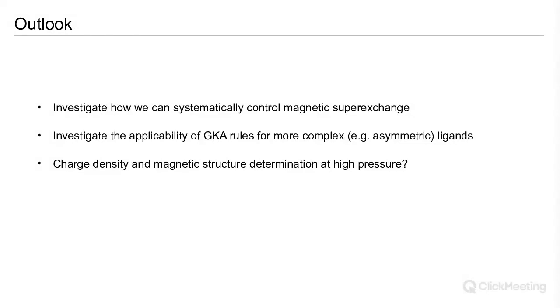One disadvantage at present is that the interactions tend to be weak. From a fundamental point of view, it's a great advantage. It means you can push them around with small magnetic fields, you can push them around with relatively accessible pressures, and it means you can study simple models, as I suggested. You don't have to worry about very long-range interactions. But any application, you want to happen at room temperature, right? So yeah, this is an issue here, but we're thinking about this, and there are ideas and routes to where we might be able to enhance the exchange through these different ligands, to explore choosing to increase these exchange interactions if we can.